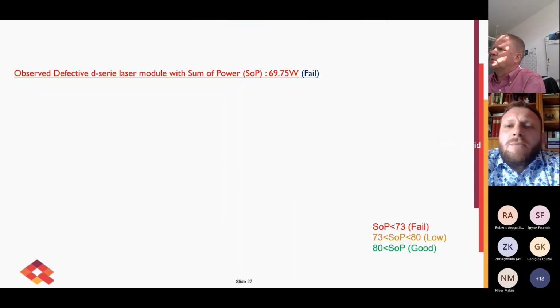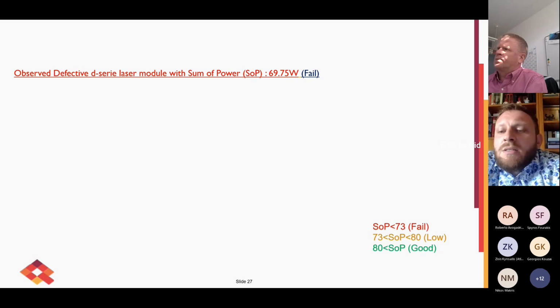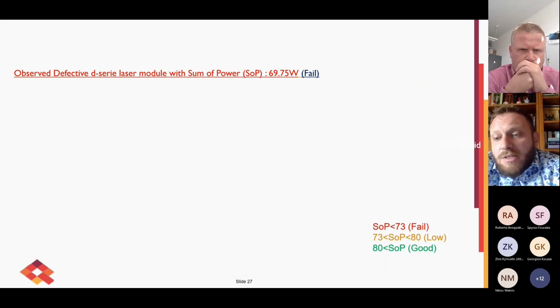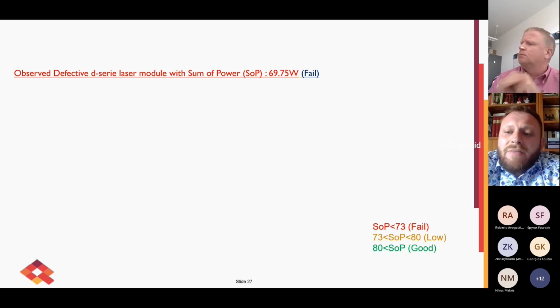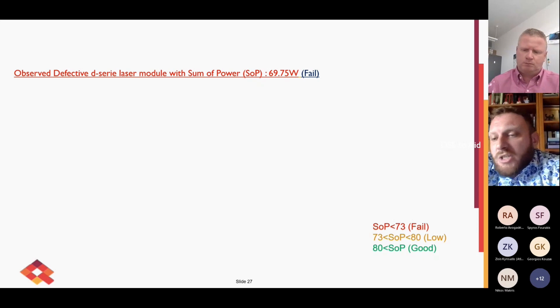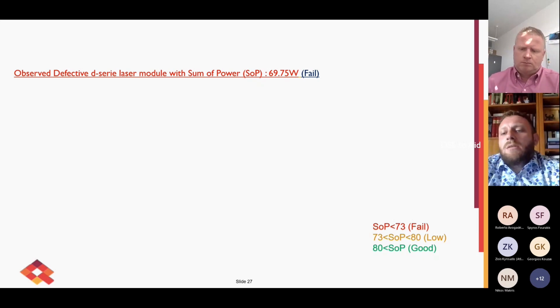I will give you a demonstration of how it works. So we found a defect laser module with a power of 69.75 watts. On the bottom right, you can see the thresholds. So pretty much below 73, it's not acceptable. Between 73 and 80, the power is low. We can consider it as okay, but what we aim to produce is power over 80.